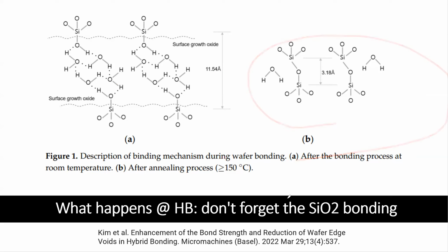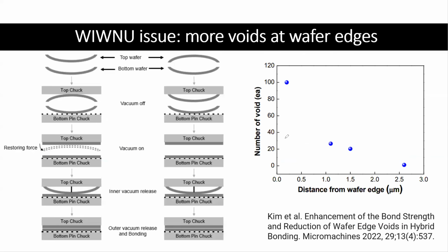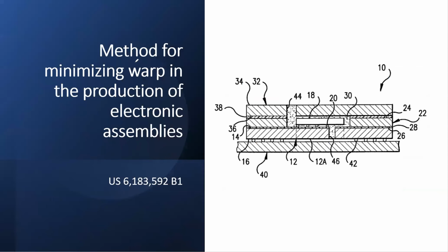Okay, so that's what I said. Don't forget about the SiO2 bonding. It's critical too. If you have bubbles, especially wafer to wafer, then you're in deep trouble. The yield on the edge of the wafer will be lower. And as I mentioned last time, you want the yield to be 100%. You cannot lose the wafer edge. That's not good. Each die you put on a non-good die costs a lot of money. So how do we reduce that?